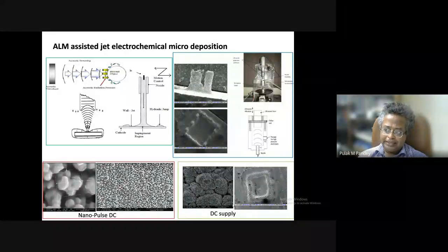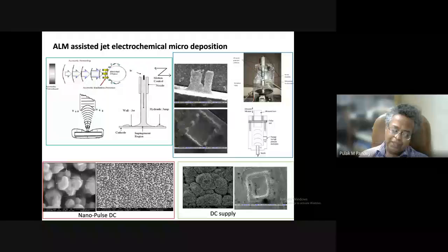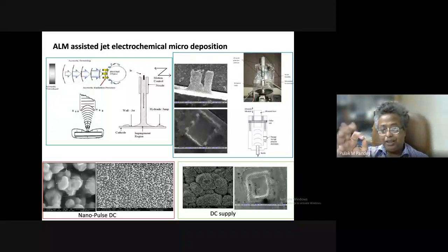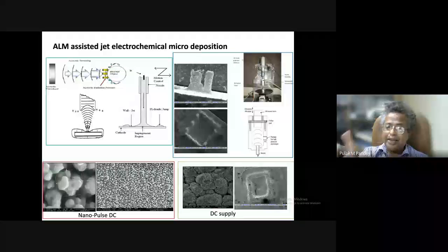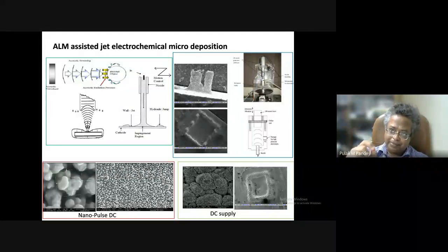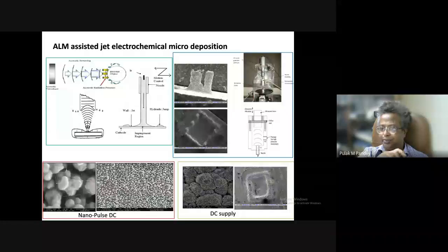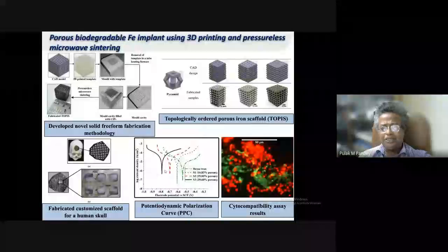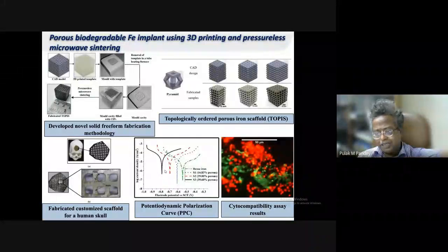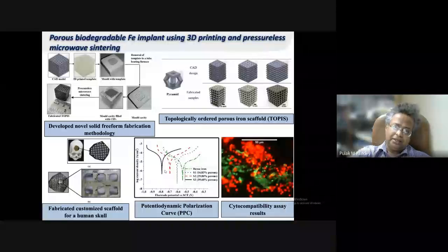So with ordinary DC supply, you get very large grain size, but once we used nano pulse DC, we get nano particles in the structure. So now we can proudly say that I can deposit a micro component, and I can ensure that every grain present in that micro component is a nano grain. So this is an entirely different kind of work which we have done at IIT Delhi. This is another very recent, and so every work has patent. Now this is another very recent work, 1 or 2 years old.